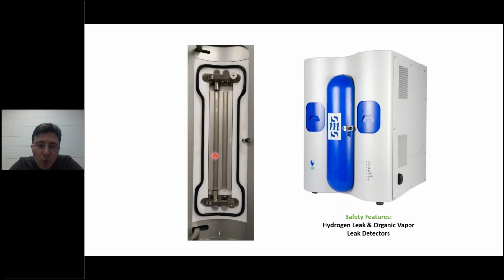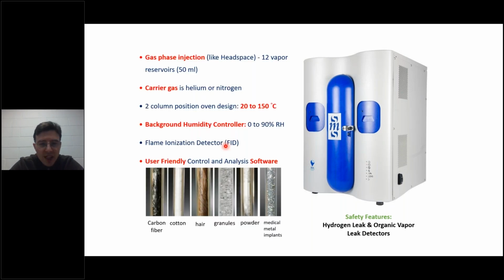You'll also notice that we can do 2 columns within this system, so we can run 2 experiments consecutively and not simultaneously. So this oven is capable of doing an experiment from 20 degrees C to 150 degrees C. Now those temperatures apply to actually doing the entire experiment at that temperature, or they can also apply to pre-activation of the sample to do before we do our experiment.